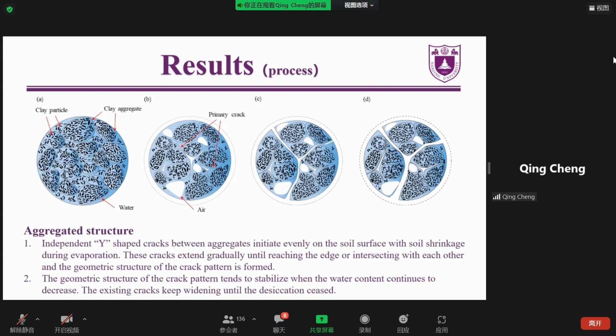First of all, the independent Y-shaped cracks between the aggregates initiate evenly on the soil surface with soil shrinkage during the evaporation. And these cracks extend gradually until reaching the edge or intersecting with each other. And the geometric structure of the crack pattern is formed. And then the geometric structure of the crack pattern tends to be stabilized when the water content continues to decrease, and the existing cracks keep widening until the desiccation ceases.